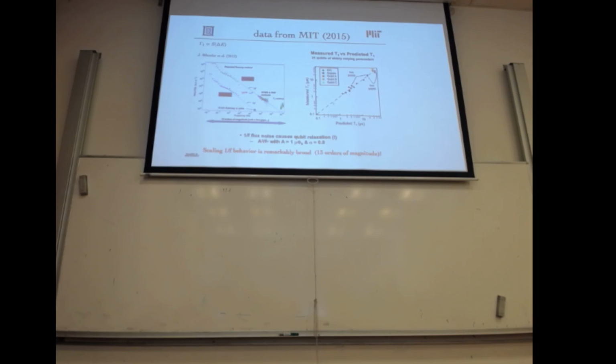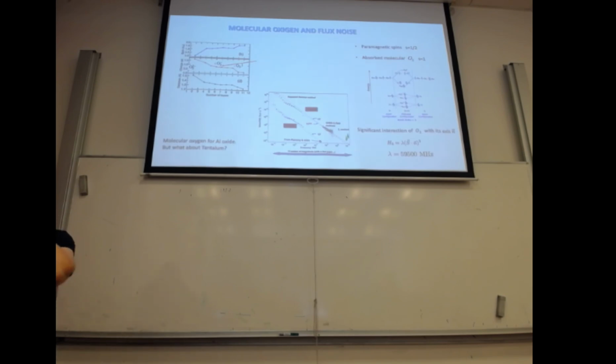And this was really very surprising, because what these plots show is that this 1/f noise that we have due to the spins is not a 1/f noise that has a natural cutoff, but indeed goes even for 13 orders of magnitude, and it's quite astonishing. And of course, the problem is how it's possible, from these spins that interact as we were thinking, these paramagnetic spins, there is no way that you can explain the presence of this very high energy.